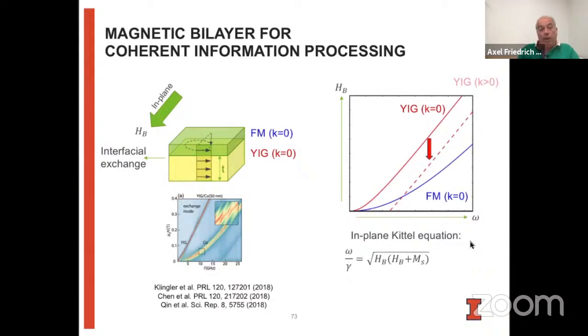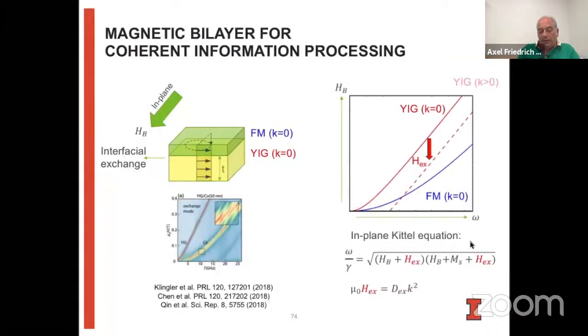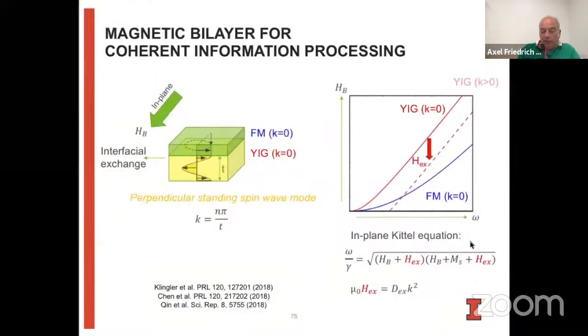One way you can get around this, and this is what you see here, is by using modes that have a finite wavelength. In particular, you can use a finite wavelength mode that is given by the thickness. So if you think about it, if you have a finite wavelength, then you get an additional exchange field contribution. This exchange field contribution will scale as the square of the wave vector. And if you have a quantized mode across the thickness of your film, then the wave vector is simply given by the thickness of your film.